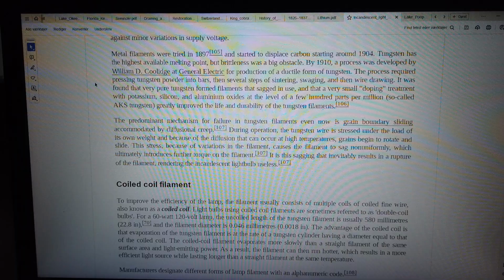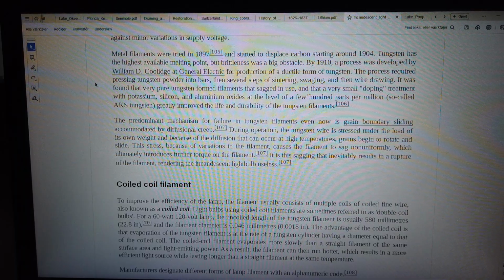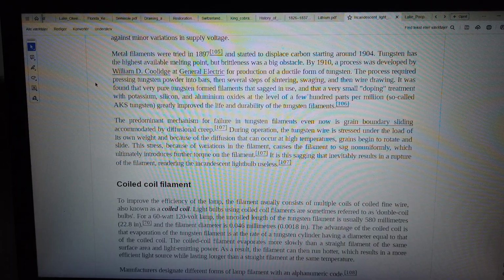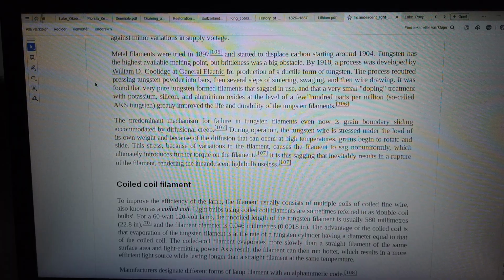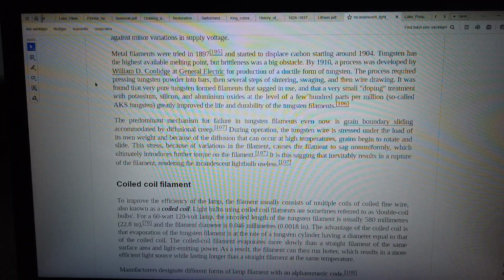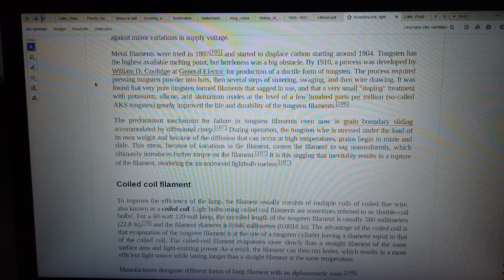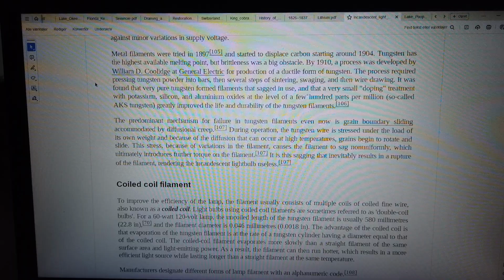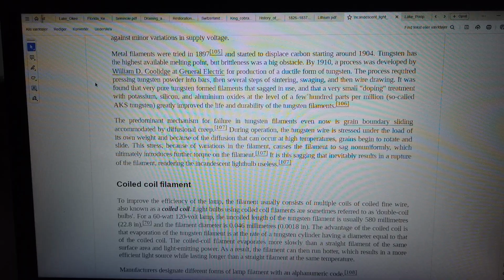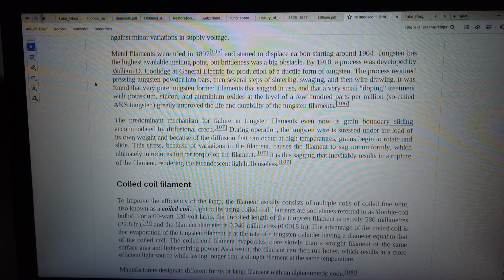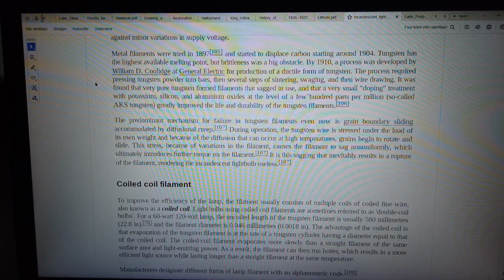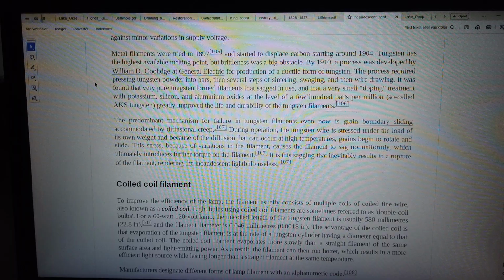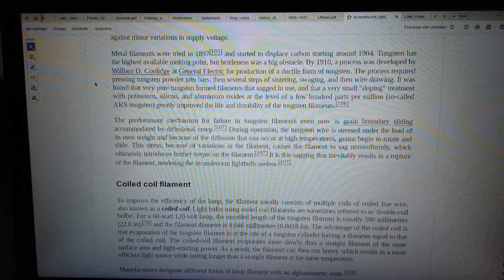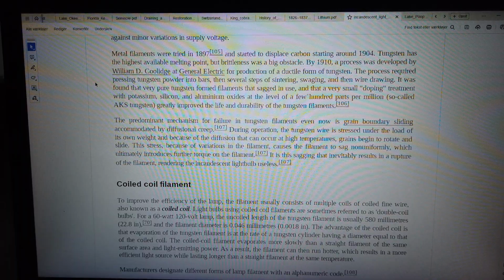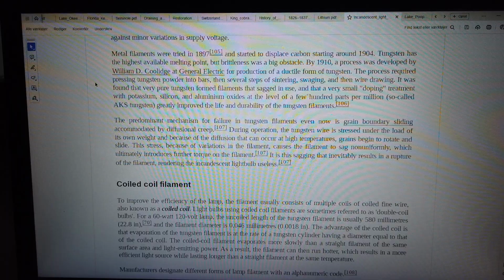Tungsten has the highest available melting point, but brittleness was a big obstacle. By 1910, a process was developed by William D. Coolidge at General Electric for production of a ductile form of tungsten. The process required pressing tungsten powder into bars, then several steps of sintering, swaging, and then wire drawing. It was found that very pure tungsten formed filaments that sagged in use, and that a very small doping treatment with potassium, silicon, and aluminium oxides at the level of a few hundred parts per million, so-called AKS tungsten, greatly improved the life and durability of the tungsten filaments.